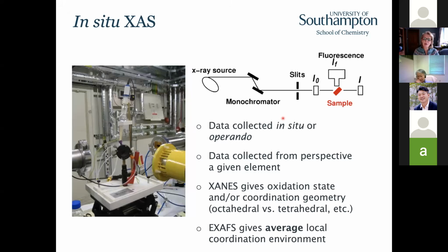And I'm a real believer that we need to make a distinction between these two terms in spectroelectrochemistry. So in situ, I mean under electrochemical control. And if we were to say operando, what we're doing is really approaching the true working environment of the material. So if you're doing battery electrodes, it's easy to do operando studies. If you're doing electrocatalysis, it's much more difficult because the fuel cell or the electrolyzer usually has a very large volume. Well, the electrolyzer usually has a large volume of electrolyte and the X-rays can't get through it. For fuel cells, we would have to go through the flow field plates and things and the current collectors. And that makes that difficult.